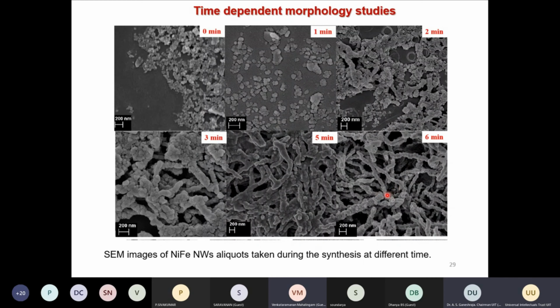We did a time-dependent morphological analysis where we can see the reaction at different times. At time 0, they look like very aggregated particles, no particular shape. After 1 minute, similar. After 2 minutes, again aggregation. At 3 minutes, we started to see some little longer protrusions, and after 6 minutes, nanowire formation happens.